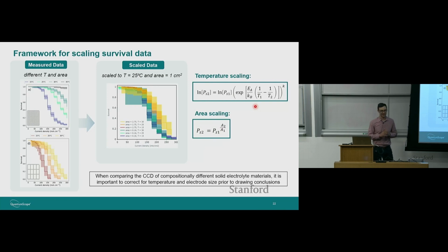And second, there's an area scaling that's basically a power law with the area of the device you measure, because again, failures will happen at a weakest link or a biggest flaw in a material. So the larger area you probe, the more likely your probe is to encounter a flaw. So there's just an area scaling relationship that then allows, once you measure a statistically valid data set at any area, you can extrapolate then to any other area. So these features have been useful in driving our analysis and driving our performance of our material.